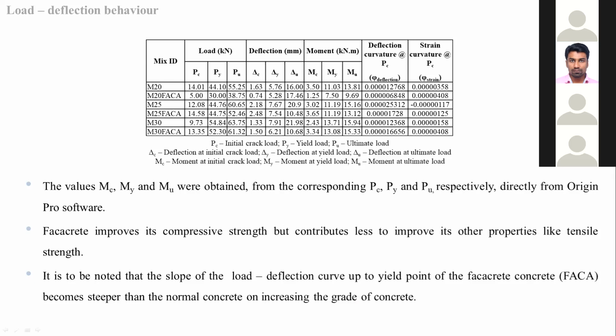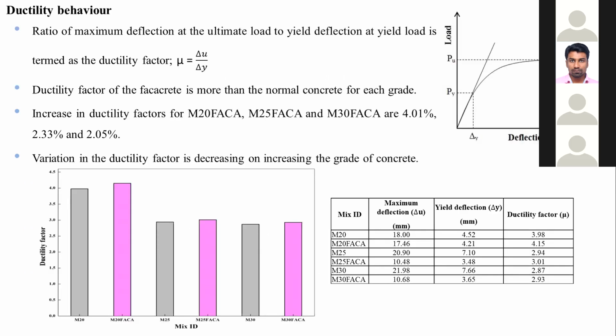We got a good result in compressive strength, but the tensile part is a little bit backward. So we have to improve that part. It will come in our future research also. And it is to be noted that the slope of the load deflection curve up to the yield point of the facacrete concrete becomes steep. That means for facacrete, we can see there is a steep slope. Now we found ductility, and we found that on increasing the grade of concrete,